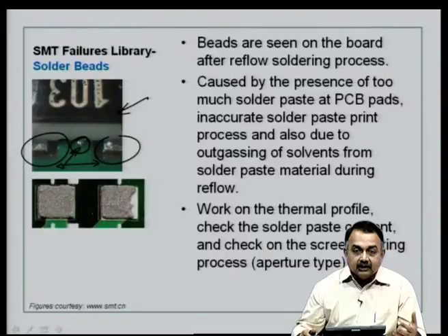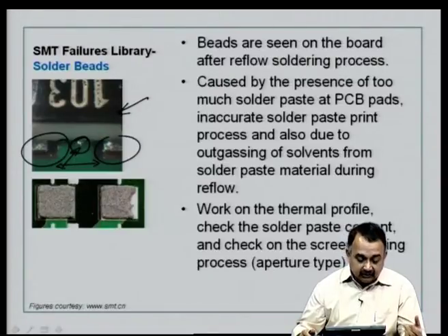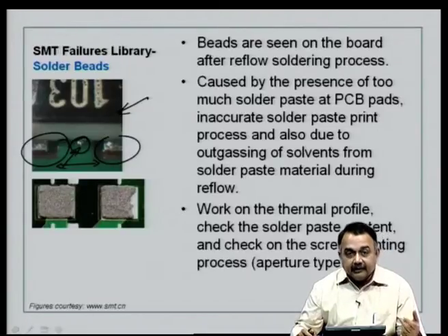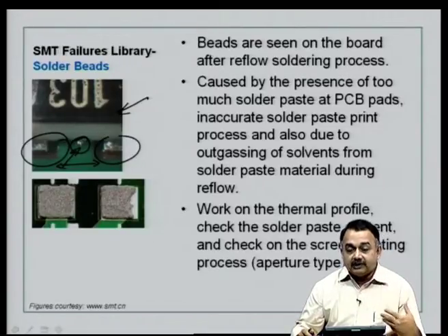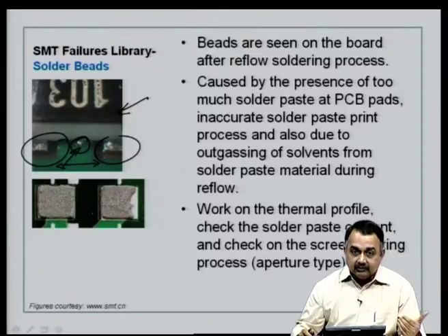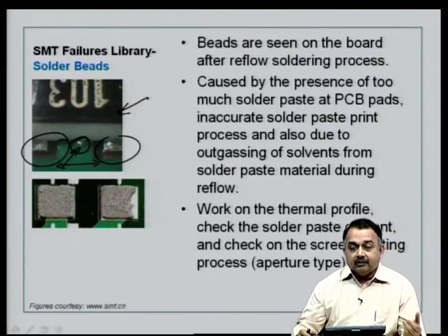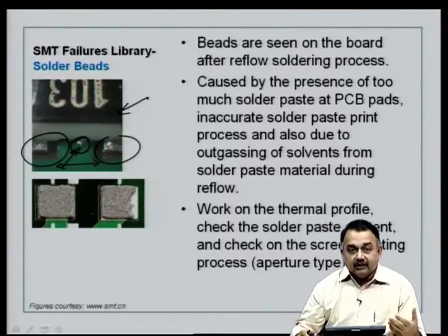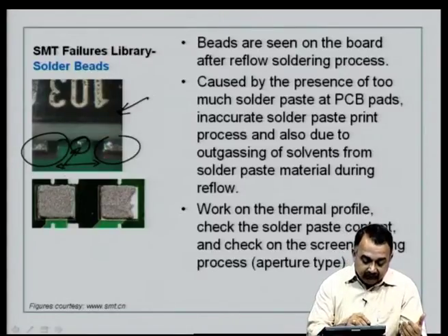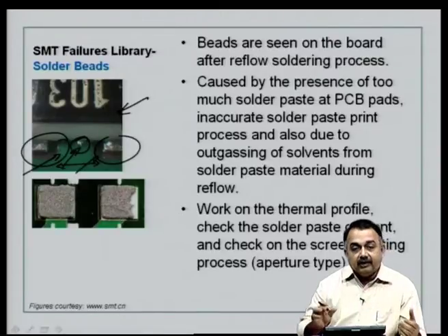And it could also result in the solder, so there is a solder mask on the board, but a lump of a solder bead which is typically tin lead, or even if you take lead free materials, they could be harmful in terms of decomposition, and if the board is subject to certain kind of a thermal stress or thermal cycling, they get decomposed, and the degassing or the solvents or the other chemicals from the solder alloy could damage the surface of the board eventually, leading into some kind of a short between very close tracks or pads.